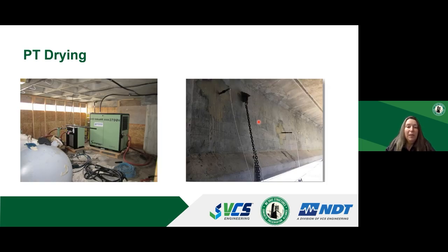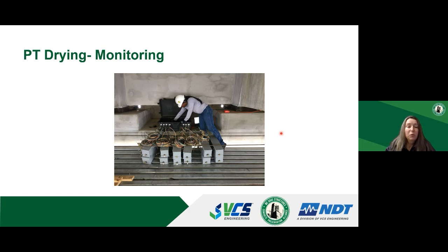This is an example from an actual PT drying project in Florida. This was done on a bridge that had bonded PT in the I-beam girders. What you're seeing on the left side of the screen is the dry air plant that was set up at one of the abutments and supplied dry air into the girders. And on the right side is a photo of the two outports that are connected through tubing to a moisture meter. On this project, we used a remote monitoring system, so that tubing was connected to this system that is being set up in this photo. The black case had a data logger that sent all the data to a website, so it could be monitored remotely.